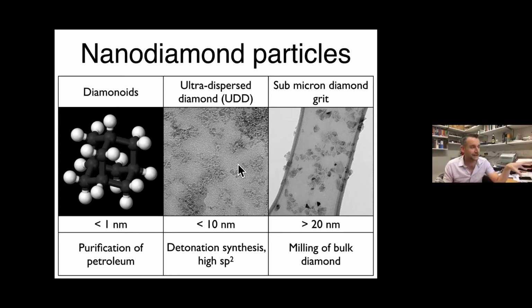There's the detonation nanodiamond, which is like this kind of amazing Russian discovery of blowing stuff up and finding little diamonds in the mess, which is incredible, with a very small particle size, around about 5 nanometers or whatever, but with a much higher sp2 content.